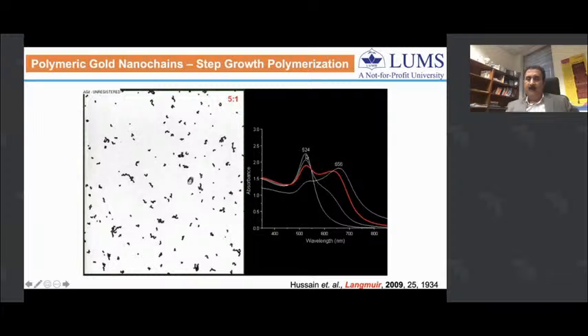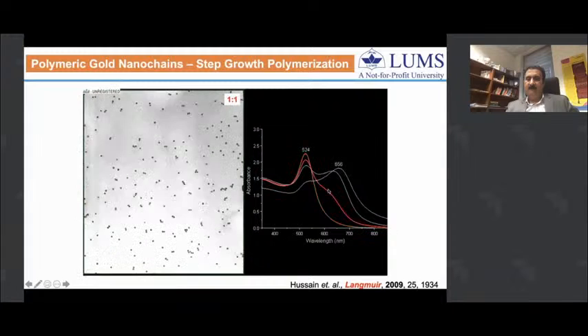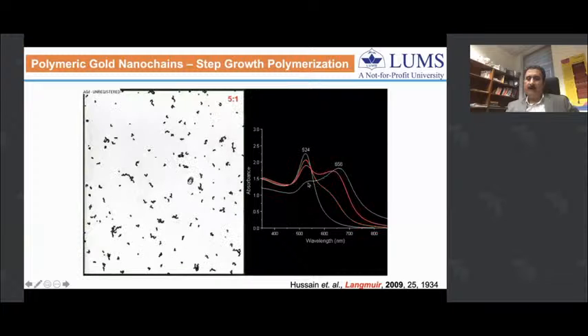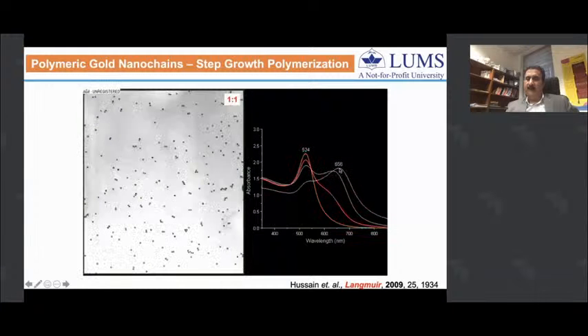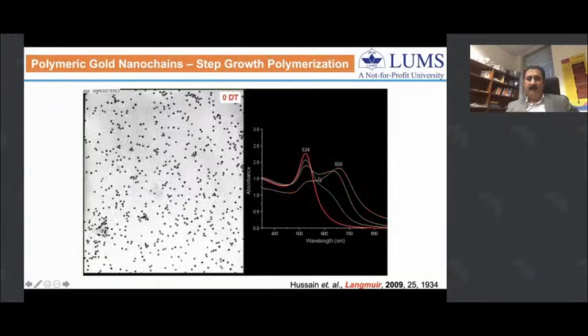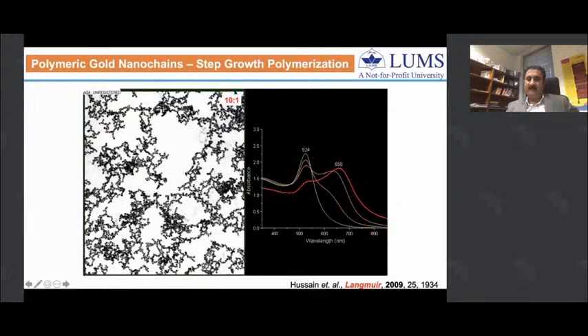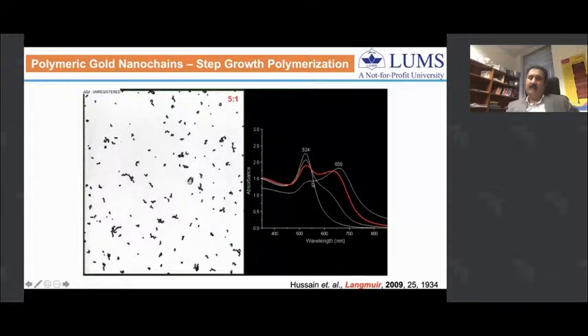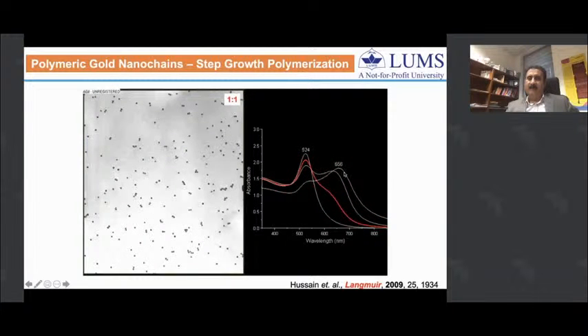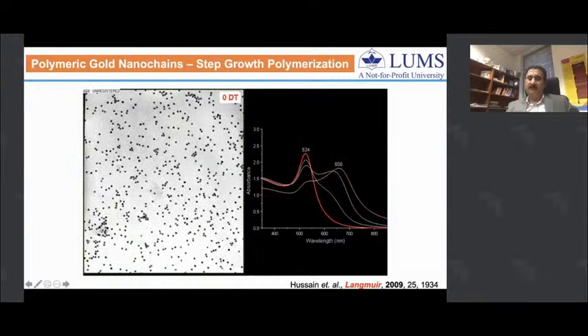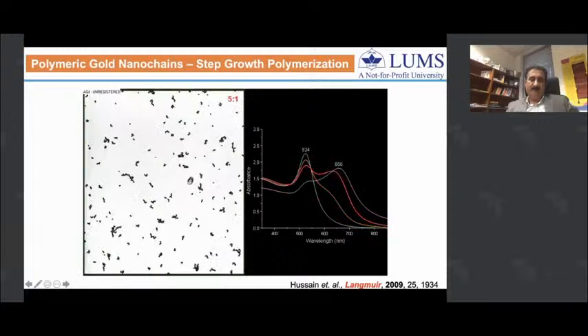Initially they have a plasmon resonance band at 524. As they form dimers and trimers, they develop this longitudinal band, which is typical of the optical spectrum for gold nanorods or gold nanowires. By cryo-TEM, we confirmed that these are actually nanowires, chain-like structures up to micrometer long, made of gold nanoparticles, existing in the solution. In this way, you basically tune the optical properties of these nanomaterials, and we believe they're really useful for optical waveguides as well.